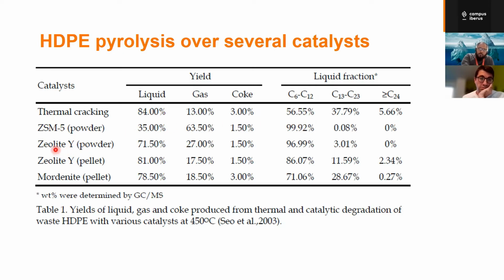If you use a zeolite Y, which is another type of zeolite, you see that compared to ZSM5, it has a better yield for liquid, and the gases are reduced, but then you can still retain the light hydrocarbons in the liquid fraction. This is the reason why I'm telling you all this contrast: what kind of product is needed in the end will decide what kind of catalyst should be used in the process. Because in the end, these catalysts decide what kind of product spectrum you will have.